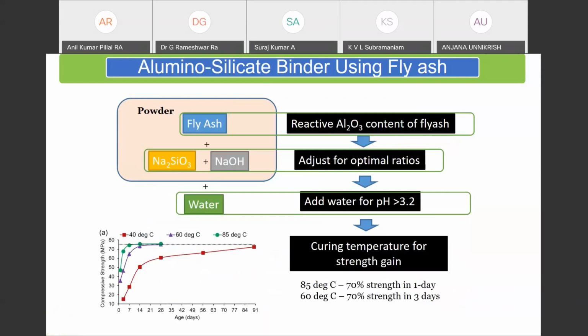Now, we at IIT Hyderabad have worked on understanding the chemistry of it, and by understanding the reactive silica and the reactive alumina that is present in it, we have developed and patented procedures which allow us to optimize the activation solution that is required. Basically, by starting with the fly ash, we characterize it and establish its reactive potential. Then we optimize the dosage of sodium hydroxide. So we are able to bring down the molarity, the processing conditions, to 3 molar sodium hydroxide, which is a far less corrosive material than 8 and 10 molar sodium hydroxide.